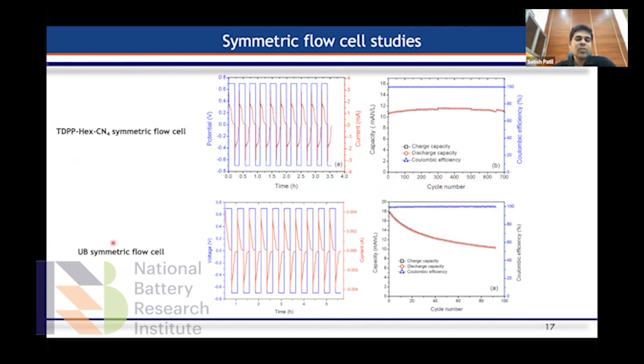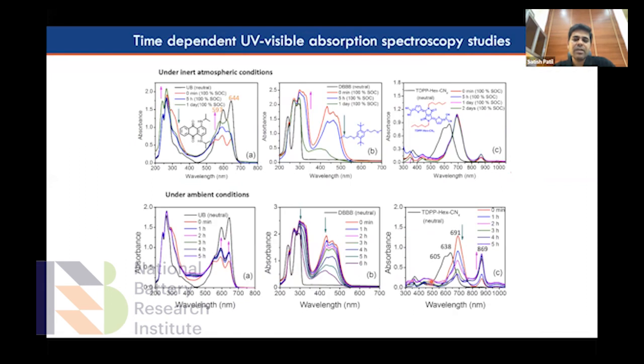But when you have this Unisol blue as a catholyte, which we purchased and used, that did not have a very stable capacity. So our anolyte is extra stable. Considering the LUMO level of this anolyte, we could go up to 700 cycles and make it a very, very stable anolyte. However, when this anolyte is in oxidized form, the capacity fades away. The lesson we learned is that our chemistry idea to rationally design these anolytes worked very well, and we could identify from this work a very stable one. And then again, we did a very detailed analysis on this one.